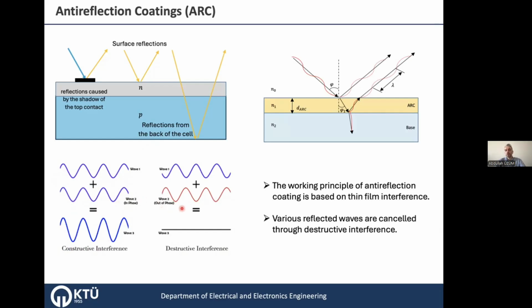But if they are out of phase, 180 degrees, then they will neutralize each other and there will be no reflection. That's the case we try to achieve with anti-reflection coatings. For example, here, N0 is the refractive index of the air or the ambient you have. N2 is the silicon here, and N1 is the anti-reflection coating for the case of a single layer anti-reflection coating.